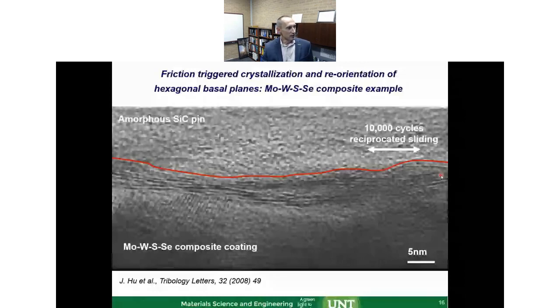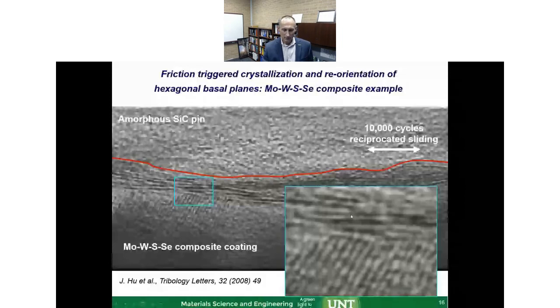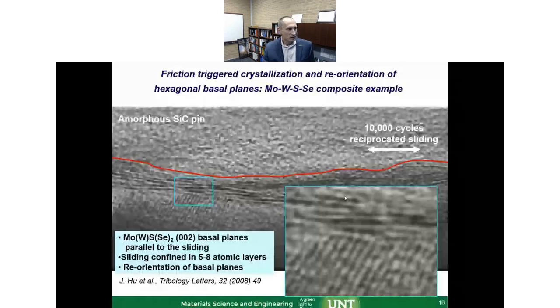But what we see here immediately, right under the silicon carbide, which is the amorphous pin, is the basal planes oriented parallel to the surface. And you can see here they're very thin. You notice here there's 5 nanometers. In fact, we can zoom in and count how many basal planes it takes, and we can see 1, 2, 3, 4, 5, maybe 6. So with this, all we need is just a few, 5 to 8 atomic layers, and they will do all the work. And it's over 10,000 sliding cycles.